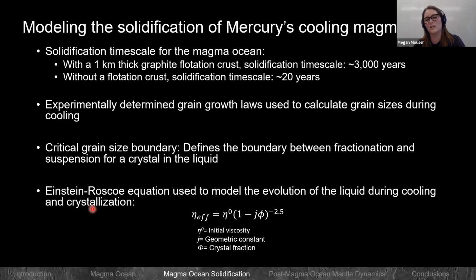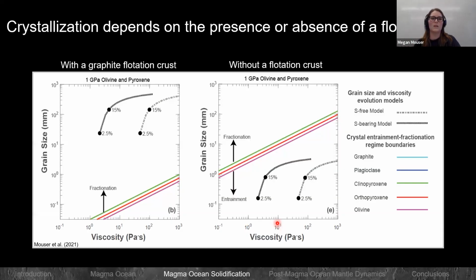And so we can use this Einstein-Roscoe equation to model what the effective viscosity would look like as you increase the crystal fraction in the system. And so you can see, just based off of the setup of this equation, it changes quite dramatically when you start adding them in. So we have all of these different steps, all of these different models that we're trying to incorporate. So let's put this into what it means for the big picture.